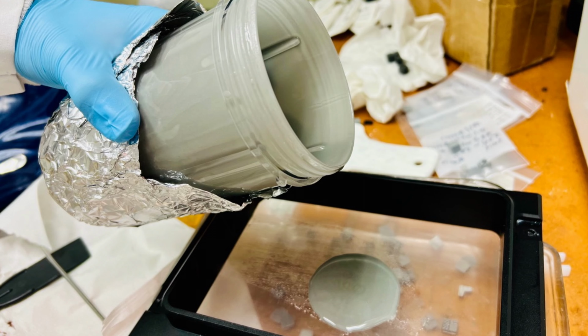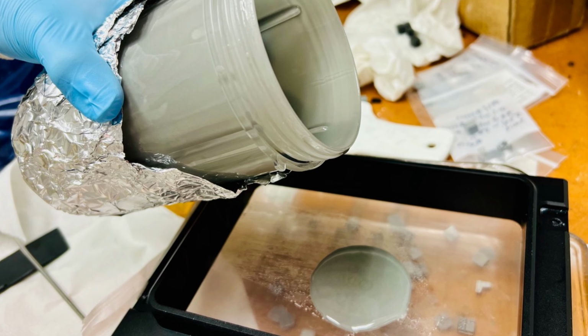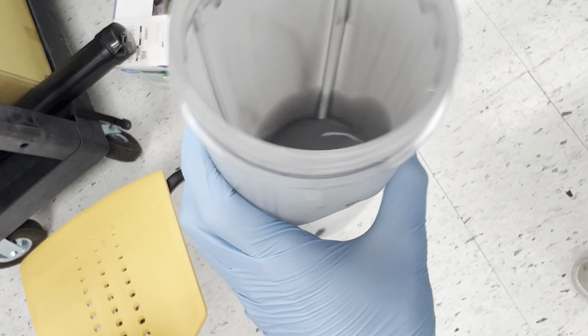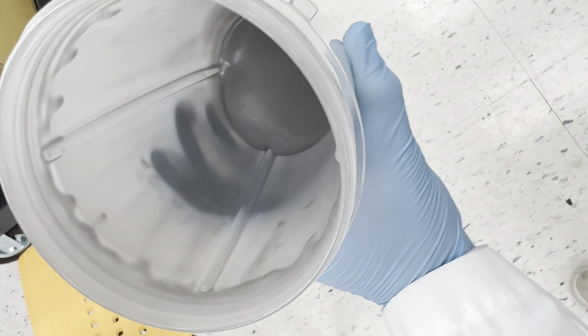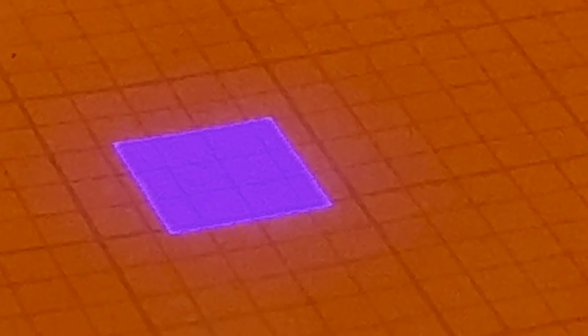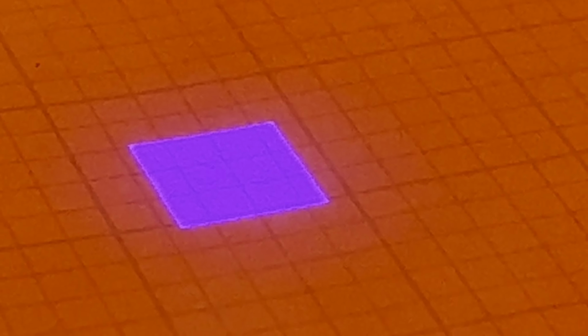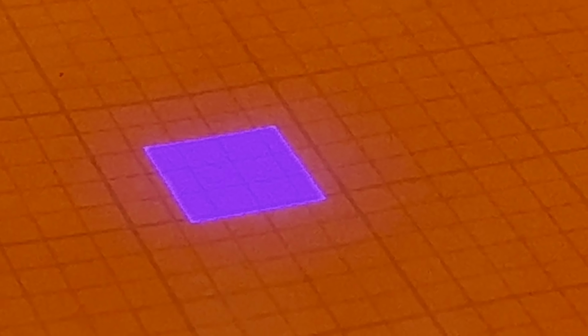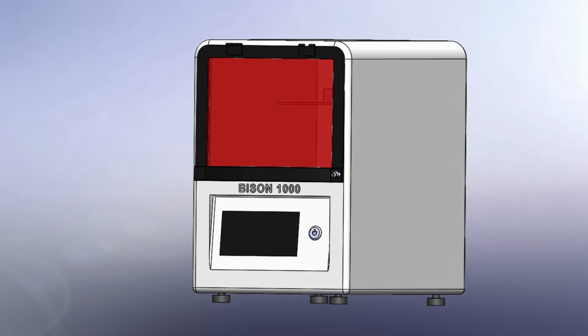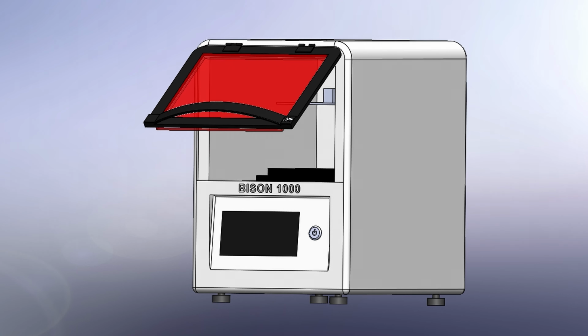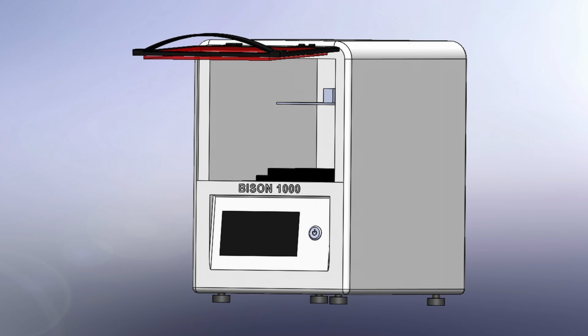Flowability is important during printing. The heat from blending or from the heater in the printer reduces the viscosity of the slurry. The 3D part is sliced into 2D layers, and the image of that 2D layer is projected with UV light. This cures a specific part of the slurry into a desired geometry and onto the printing bed.